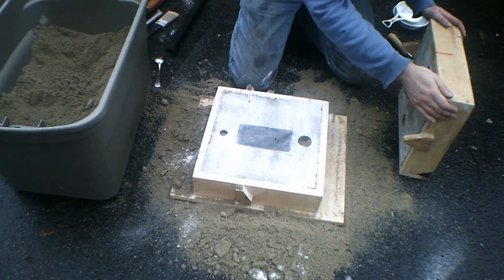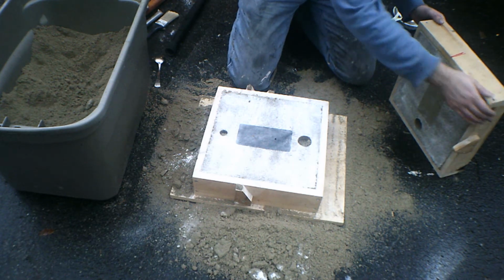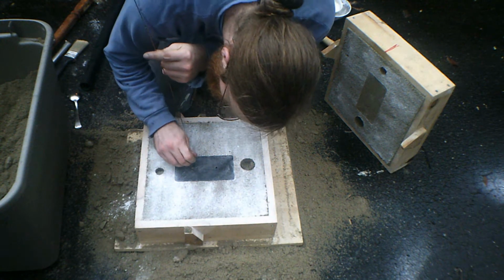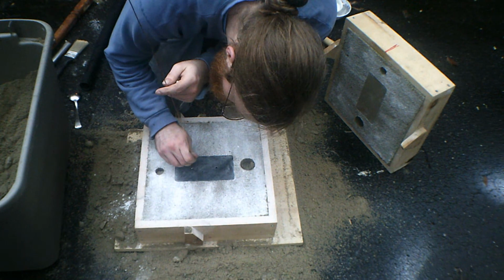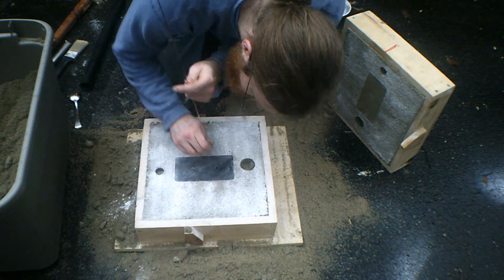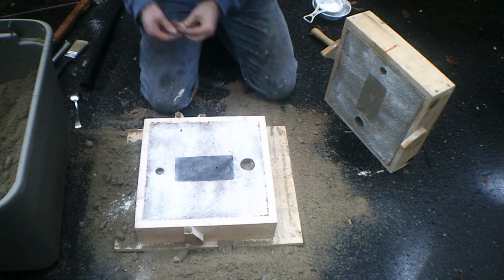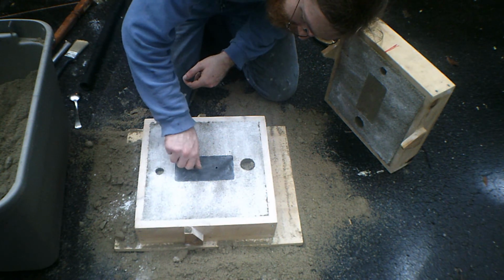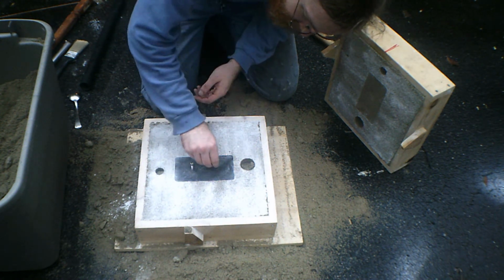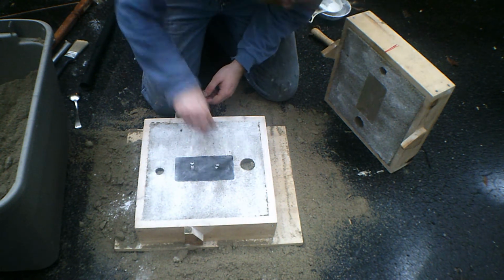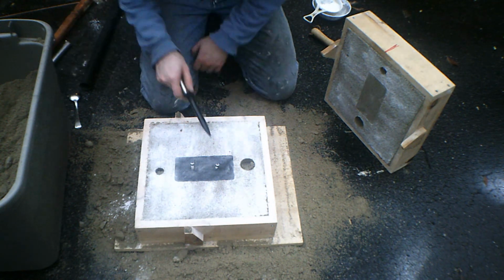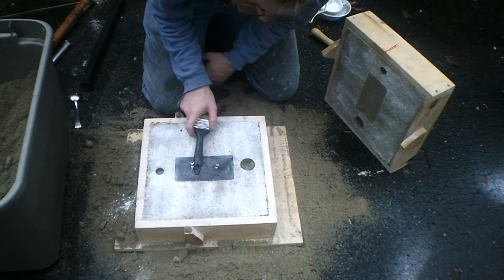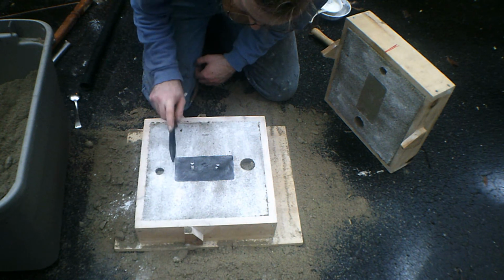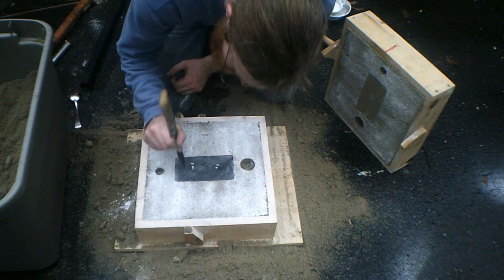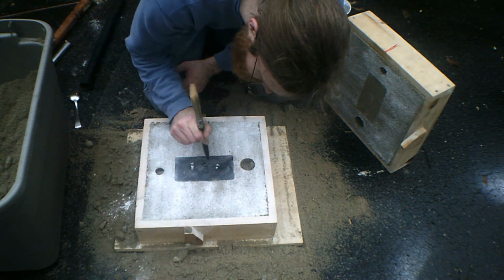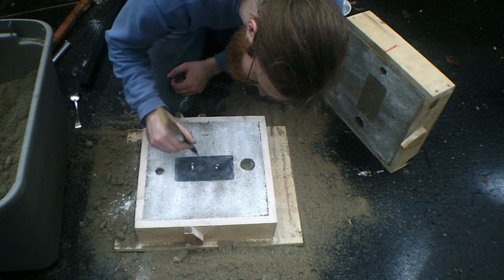Having a couple of holes in the pattern to draw it out with is completely necessary, and I had a little bit of sand fall into mine, so I used the vent wire to scoop that out before putting a couple of screws in. And then by rapping the pattern, you enlarge the cavity that it made a little bit so that it pulls out more easily. The dimensional accuracy is not usually something to be worried about, but having everything stay where it should be is something to be worried about. You can see in a moment when I draw this out, it comes out almost completely cleanly.